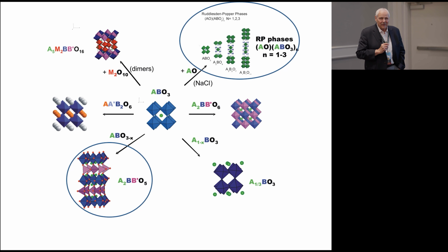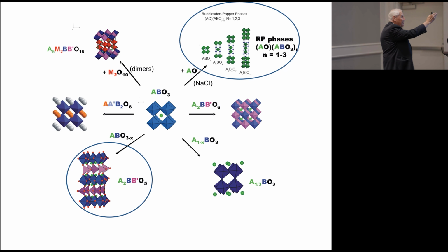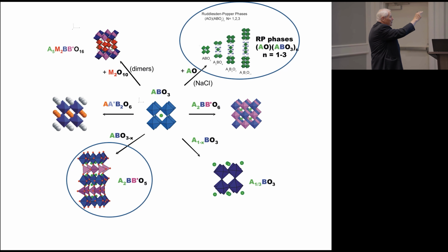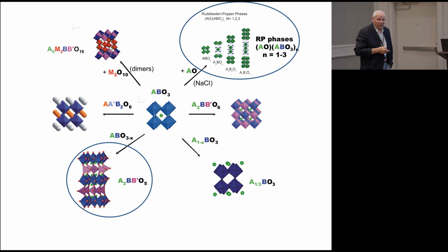And to my astonishment, there are 1,200 of these things now, according to a recent review article. You can do substitutions on the A site. You can create vacancies on the A site. But the two things we're going to talk about are the intergrowth possibilities, the most famous one being with the sodium chloride structure to produce the Ruddlesden-Popper phases. And we're going to take oxygen out, and we're going to end up with brownmillerite and brownmillerite-related phases. Those are the two we're going to spend most of the time on.